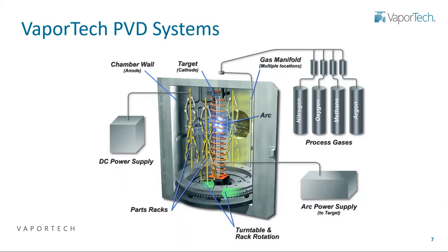One of the nice things about this configuration of having that target material in the center is that it's depositing material throughout the 360 degrees around the chamber. In some configurations, you have these sources mounted on the walls, which is then spraying material inwards towards the inside of the chamber, which is also a good way of doing it. We just prefer for most of our applications to spray from the inside out. It has a few advantages. Let's see what else we have in the chamber.